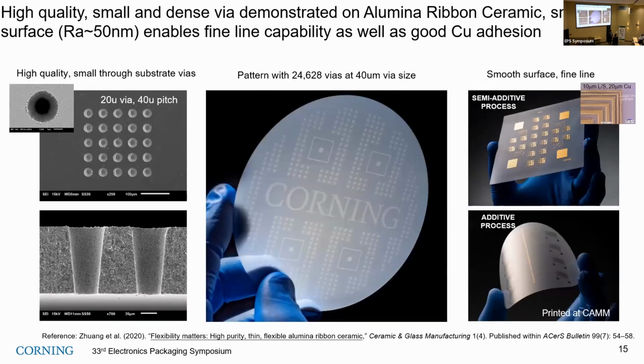We also demonstrated making high density via patterns in this alumina, used for heterogeneous integration for thermal management, or also for 5G 3D inductor type filters that you can fabricate on this. So you need through alumina vias, and we are able to make down to 20 micron via diameter with 2 times the via diameter, 40 micron pitch. We also tested a lot of filters fabricated on this with a semi-additive process, and we don't see any adhesion issues. We also did additive processes like printing on this alumina with good adhesion and electrical properties.